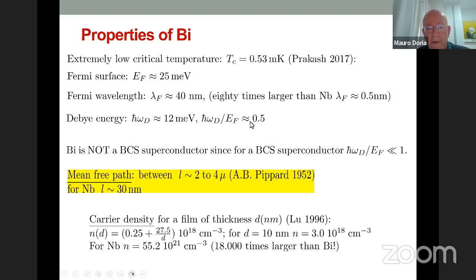So you see that this is not a BCS superconductor, because when we do BCS theory, we assume that the Debye frequency is much smaller than the Fermi energy. So there is something strange in bismuth. Moreover, and very interesting, this is side information of this seminar, the mean free path of bismuth is of order of a micron, whereas niobium is 30 nanometers. So it's much larger for bismuth. Then you can make assumptions and measure the electron density in bismuth. This has been done in the past. It's not very large. I mean, niobium is 20,000 times larger than bismuth.